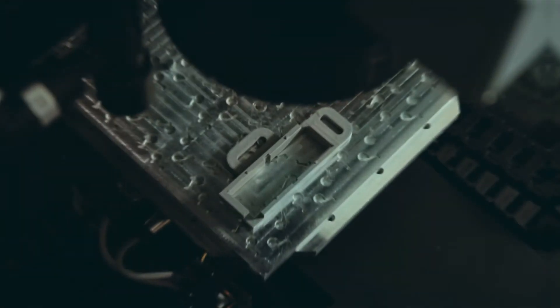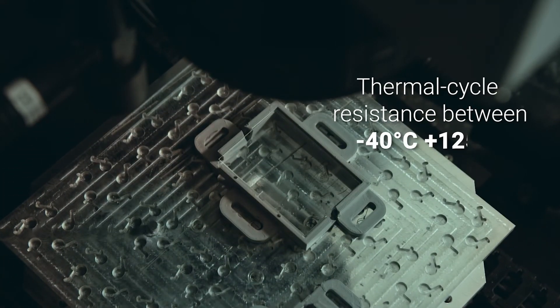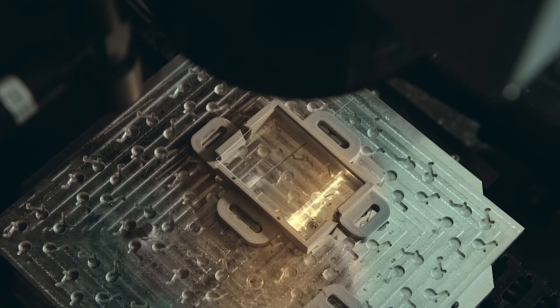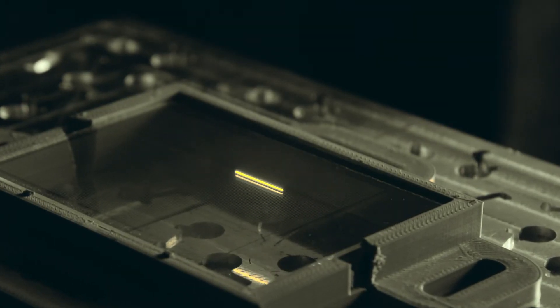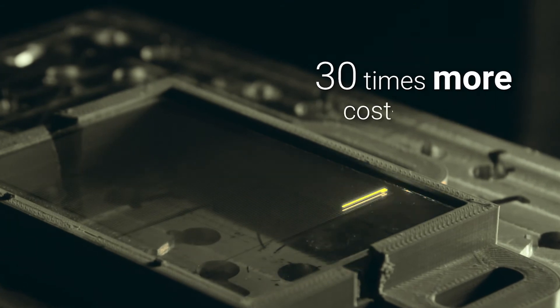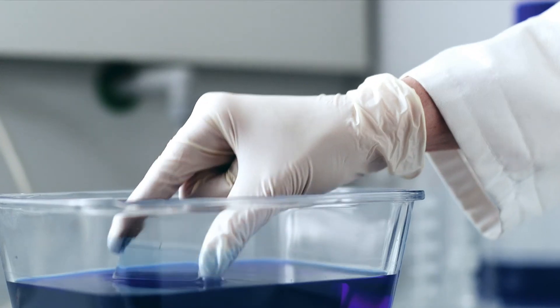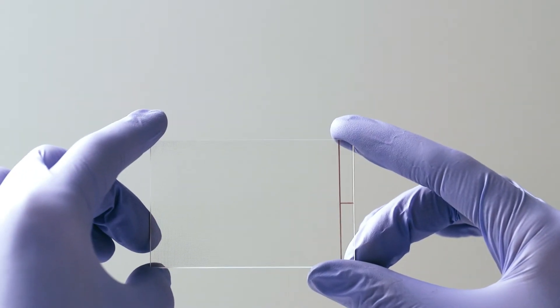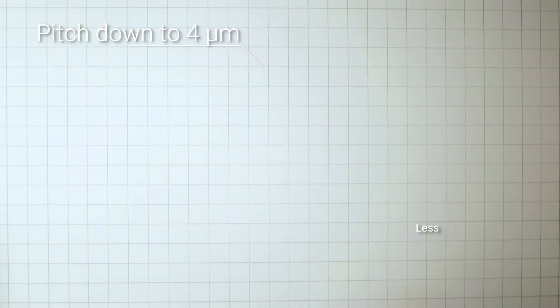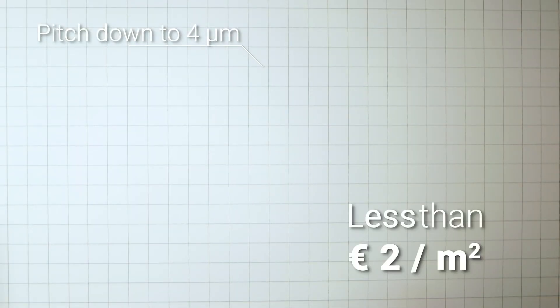And due to its increased thermocycle resistance, touch screens can be used in a broad range of consumer and industrial use cases. SAIL uses easily accessible materials, therefore it's almost 30 times more cost-effective than ITO. The result is a functional layer that's 99% transparent and invisible to the eye, with a manufacturing cost less than 2 euros per square meter.